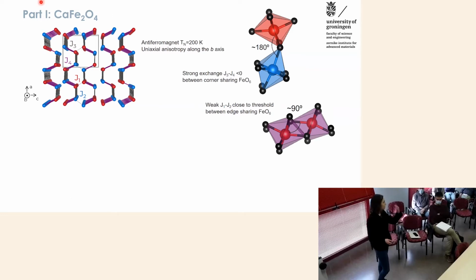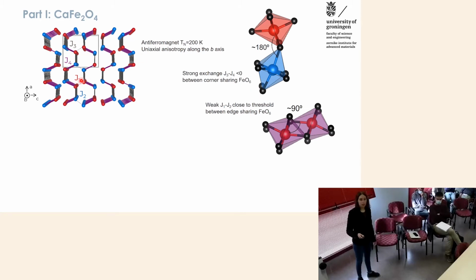armchair chains, which are running along the z-axis, and each chain is weakly connected to each other. And the reason for this is that the J3 and J4 interactions are between iron atoms, which are connected through oxygen. So this is oxygen-mediated superexchange with a bond angle of about 180 degrees, which is strongly antiferromagnetic. While in the case of the interchain exchange J1 and J2, this angle is around 90 degrees. So it's close to the threshold between antiferromagnetic and ferromagnetic coupling.